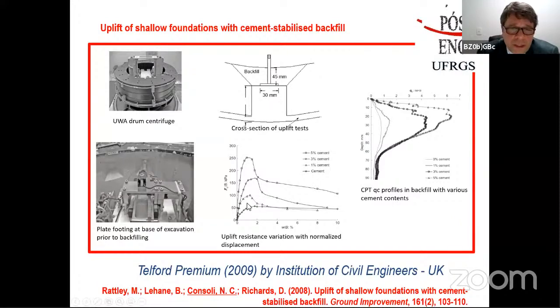Then if we put 1% of cement, we double the strength, the force needed to pull it out. If you put 3% of cement, you increase it from 50 to about 170. And if you put 5% of cement, you increase even more, to 250, let's say.